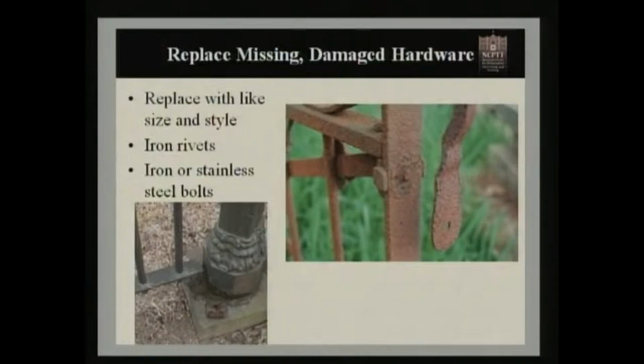A lot of times iron rivets were used. For example, in the photograph to the right, we have an iron rivet that's rusted, it's corroded, the heads have come off, and it's allowing this fence gate handle just to swing freely. We could very easily drill this out and put a new iron rivet back into it. You can still obtain iron rivets. They can be set either hot, or if they're small enough, they can be done cold.